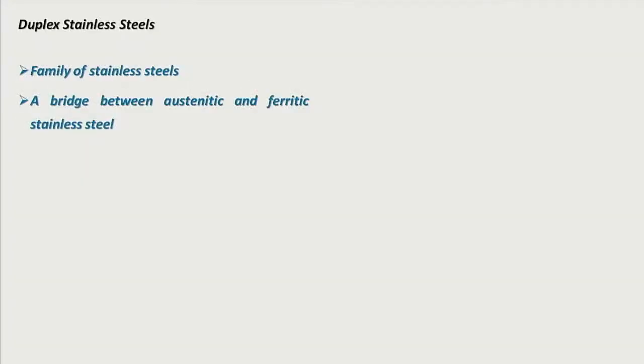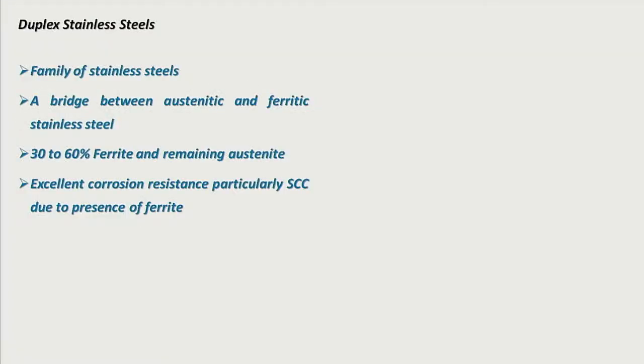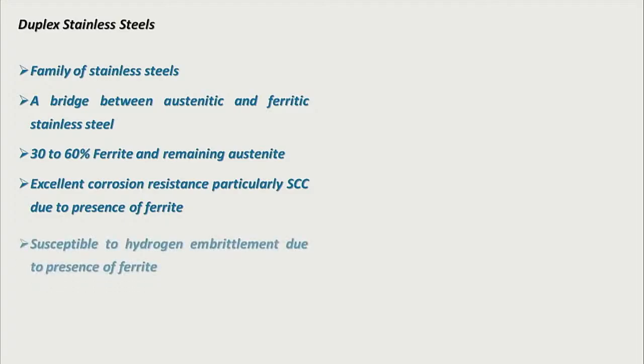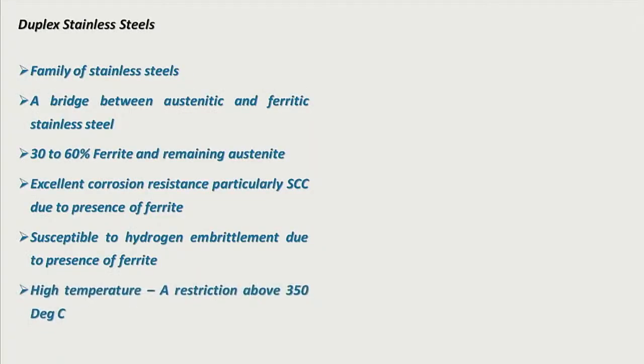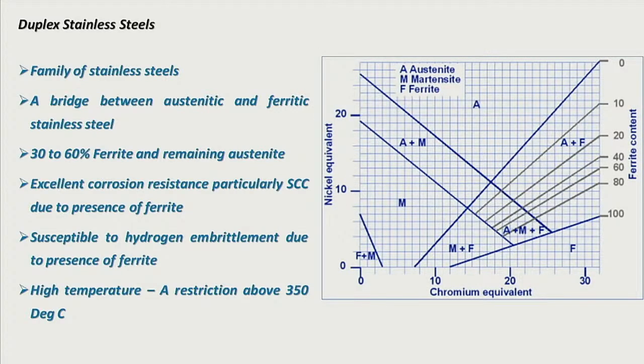So basically duplex stainless steel is a family of stainless steel. It is a bridge between austenitic stainless steel and ferritic stainless steel. This material contains 30 to 60% of ferrite phase and the remaining austenite. It has excellent corrosion resistance for stress corrosion cracking due to the presence of ferrite. However, the same ferrite makes the material susceptible to hydrogen-induced cracking. So this material is particularly restricted beyond application at 350 degrees Celsius because of the formation of various secondary phases that we will see in the upcoming slides.